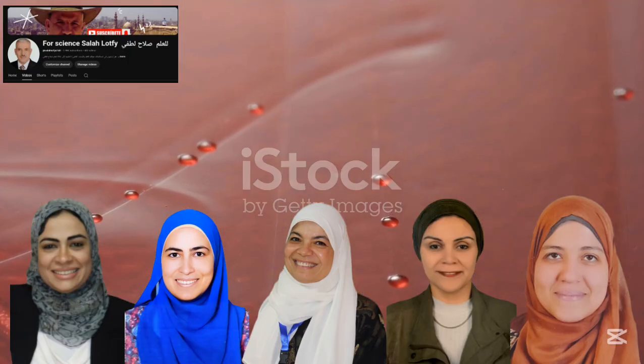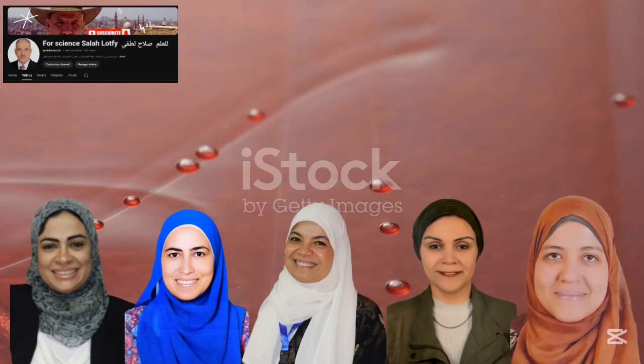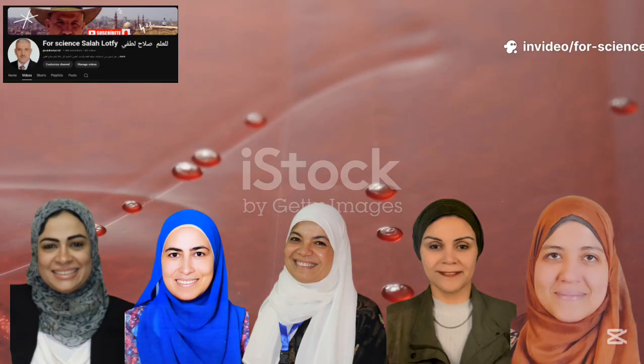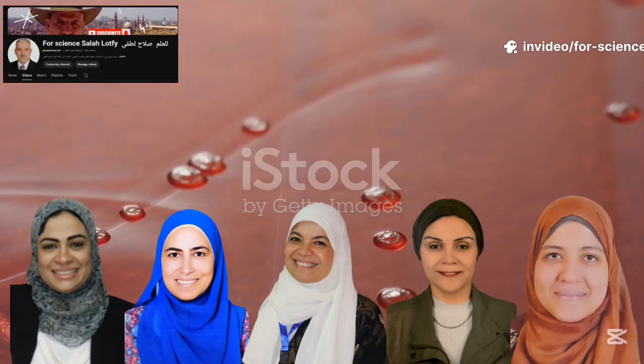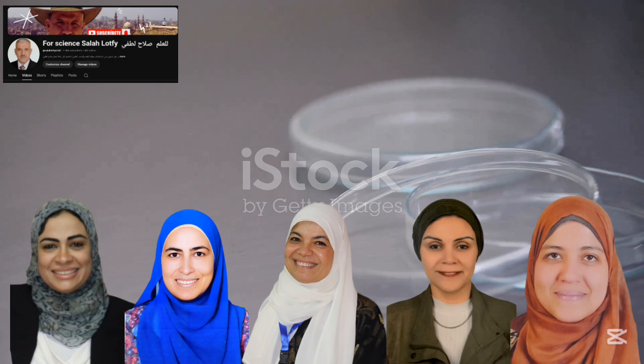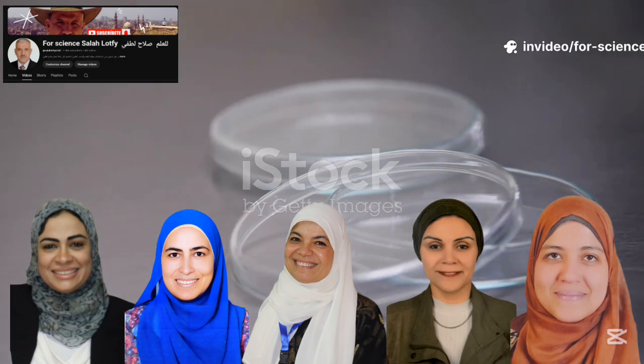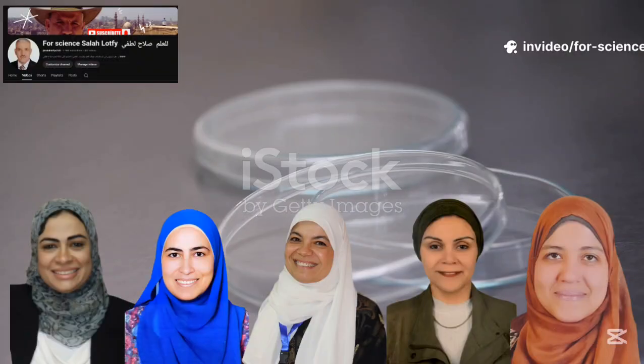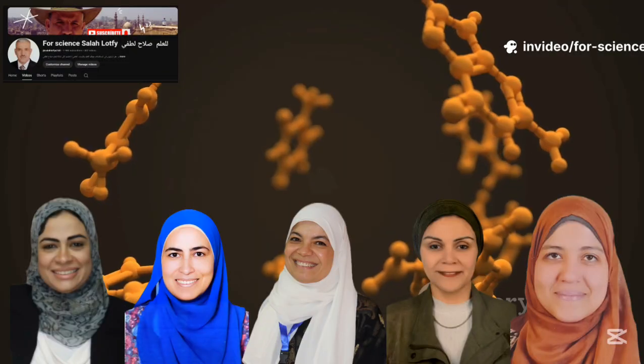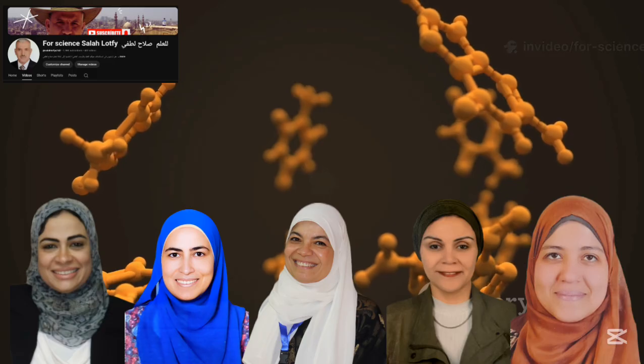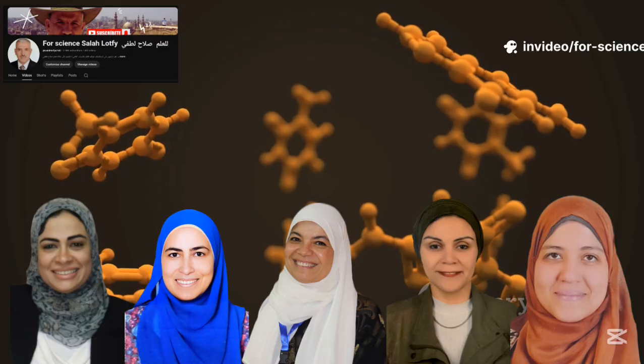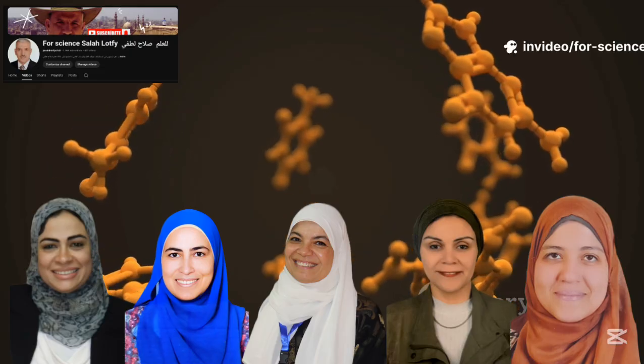The dressings were tested against bacteria and fungi: Staphylococcus aureus, Bacillus subtilis, E. coli, Pseudomonas aeruginosa, and Candida albicans. The results were impressive. Dressings with 5% lavender oil showed the strongest antimicrobial effect, with inhibition zones reaching 31 mm against Bacillus subtilis. The synergy between Ag-ZnO nanoparticles and lavender oil amplified the antibacterial effect by disrupting membranes, generating reactive oxygen species, and preventing cell division.